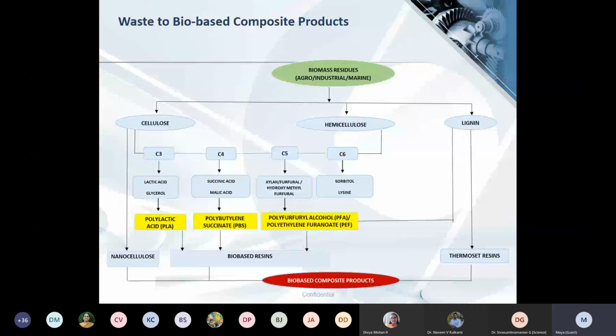an interesting thermoset resin. Then you can also extract hydroxymethyl furfural, which can be converted to FDCA, which is furan dicarboxylic acid. And that, when polymerized with ethylene glycol, will give you polyethylene furanate. Now, currently, Avantium, a company in Netherlands, is planning the industrial launch of PEF, which is polyethylene furanate, somewhere in 2023 or 2024. And it is assumed that once PEF is launched, it is going to replace the PET in drinking bottles. Now, PEF is supposed to have improved properties over PET, and it is 100% bio-based. It's completely derived from plants, and it is not biodegradable, it is recyclable.